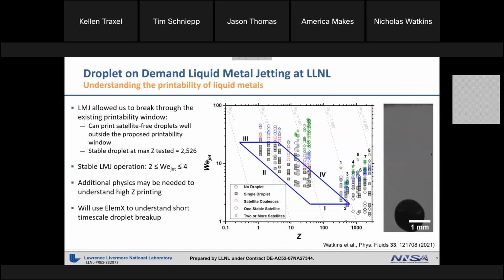The takeaway is that you can essentially jet any metals based on the fact that we were able to successfully jet pure germanium, which is the most difficult metal to jet. The video to the right shows the ejection of a satellite-free germanium droplet at a Z of around 2500, the highest Z reported to generate a single droplet. This was all done with a pneumatic printhead, which operates on the millisecond timescale. We plan to use the ElemX to understand shorter timescale droplet breakup, as it can create droplets on the order of 100 microseconds. Next slide.